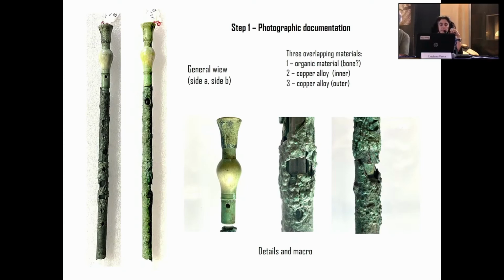Then we saw, and it was confirmed by Stefan and Kamila, that there are three different materials, three different overlapping layers. The bone, the organic material, a layer of copper alloy, and a second layer of copper alloy on the top. And the two layers of copper alloy are often melted together, probably because of the heating during the eruption and other situations during the burial.